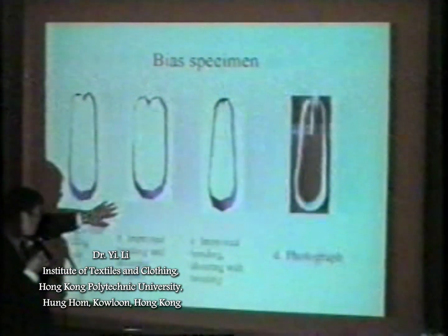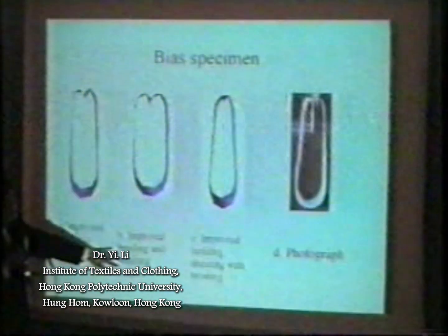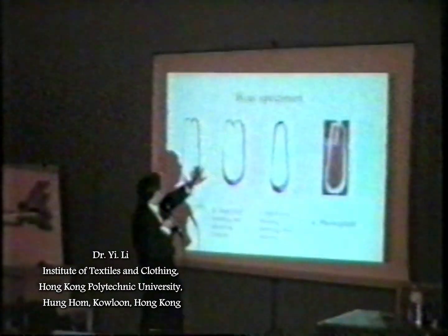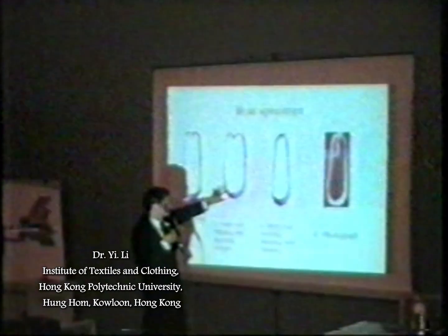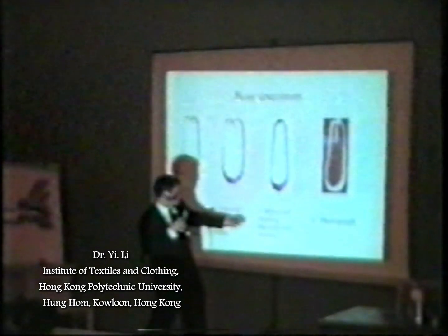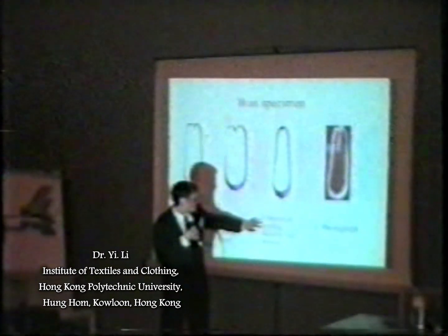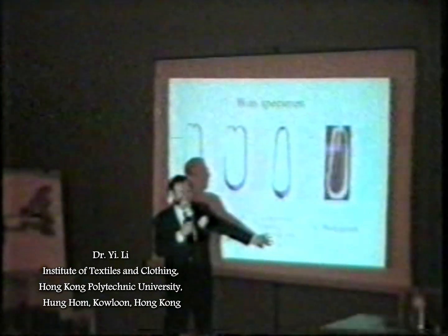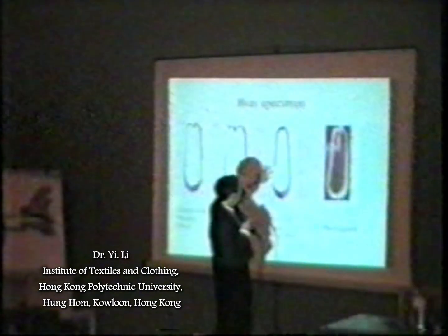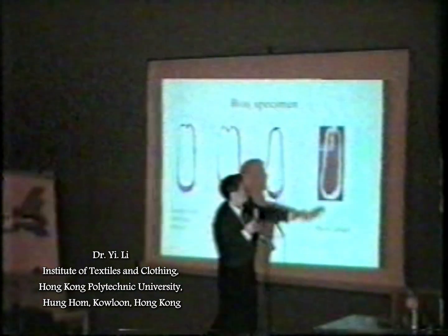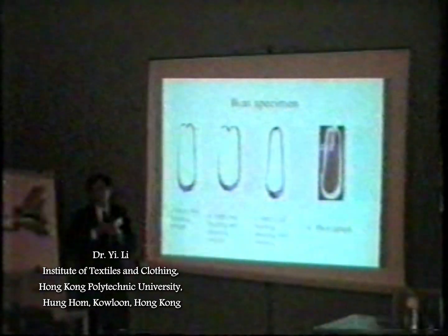With this one, we improved with the bending and shearing, and it does not improve too much. However, when we consider the bending and shearing together with the twisting, it becomes very close to the experimental results.